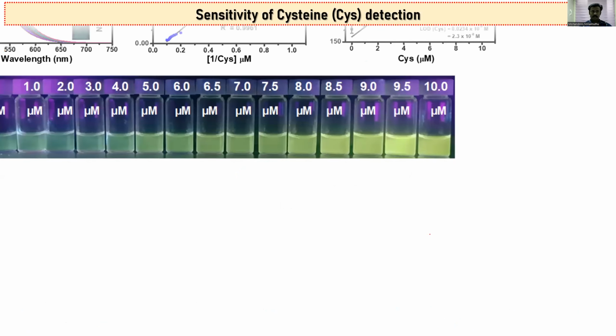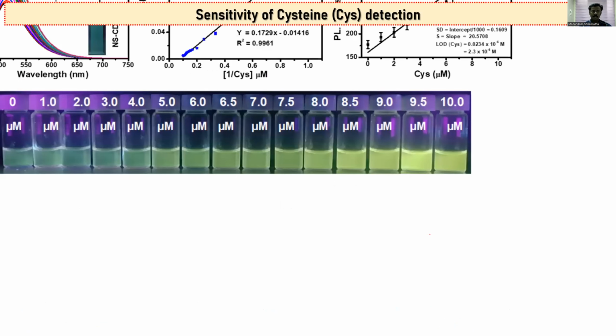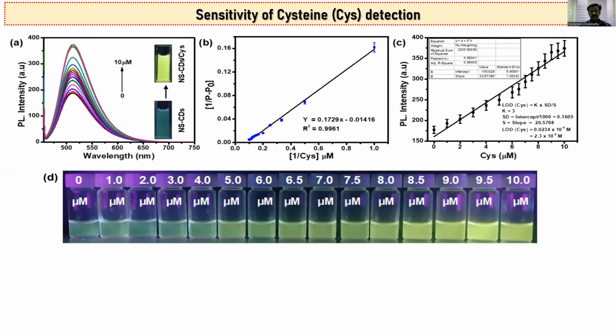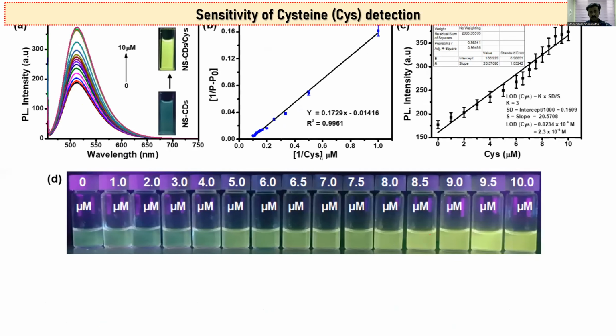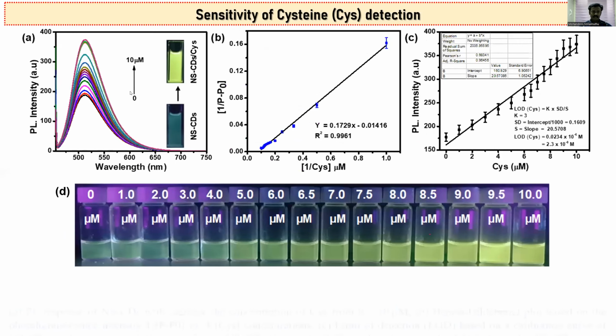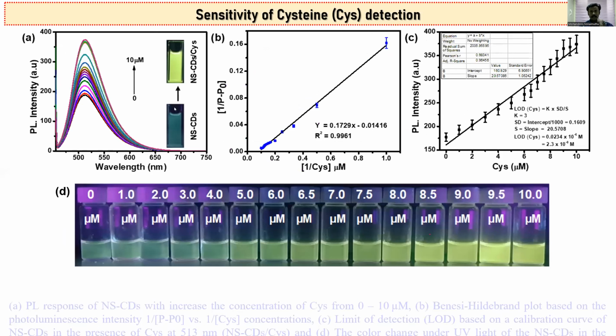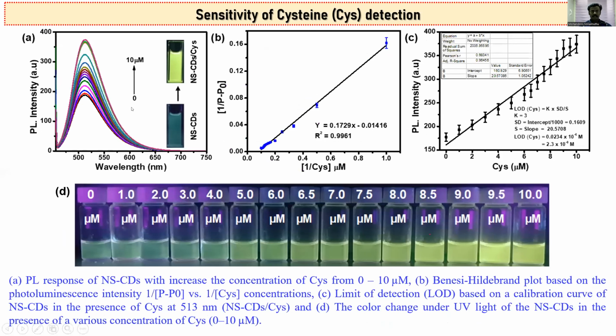The next one is the sensitivity of cysteine detection. The photoluminescence intensity at 513 nanometers gradually increased with the increase in cysteine concentration from 0 to 10 micromolar. This shows that the carbon dot solution could be used as a photoluminescence probe. Also, in the inset of figure A, the green emission appears as a strong yellowish-green color upon the addition of cysteine at various concentrations.